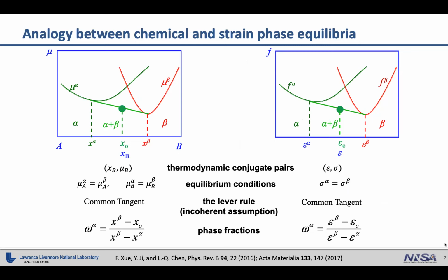And the multi-phase regions in the chemical phase diagram are determined by the lever rule, which is a common tangent between the Gibbs free energies of the two phases. And likewise, we can also make use of the common tangent construction to determine where the two-phase regions should be. And what's more, using the lever rule, we can quantitatively estimate the volume fraction or phase fraction of the different phases in these two-phase regions.